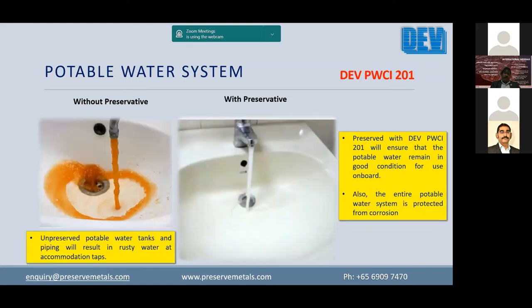In the same way, the other problem we find is when the potable water system is commissioned and then left, there will always be residual water in the tanks. If it is left in the system for longer, you will find internal corrosion of the carbon steel bare metal, leading to the brown water issue when they start operations. In order to prevent it, there is a potable water corrosion inhibitor.